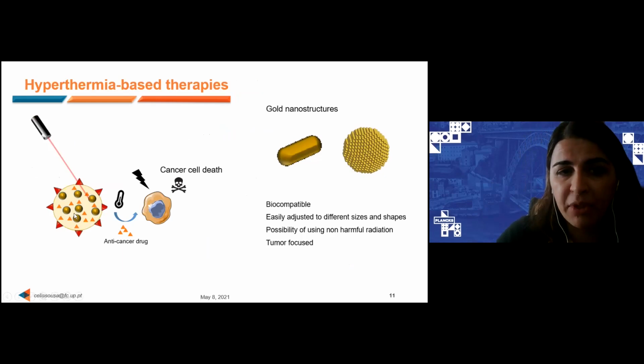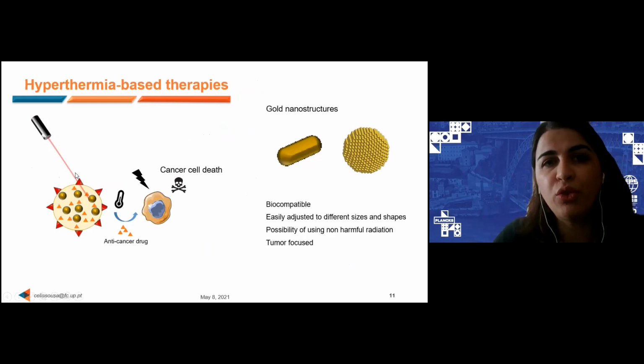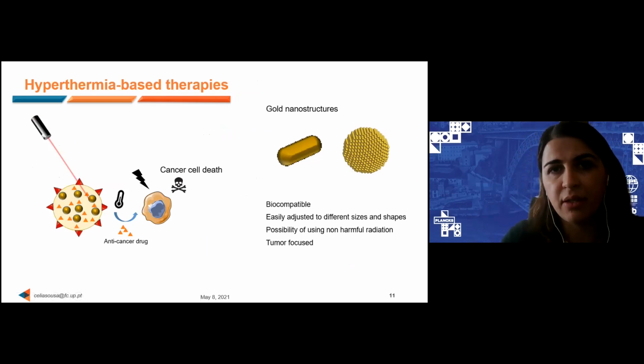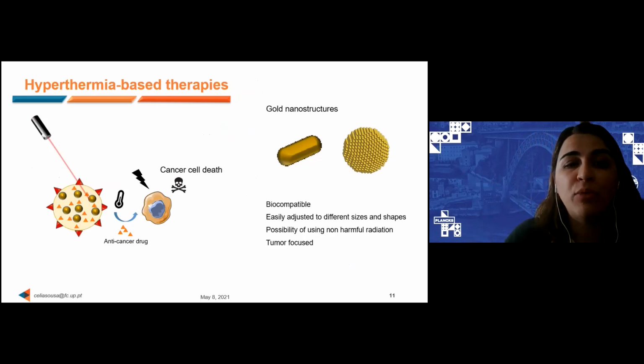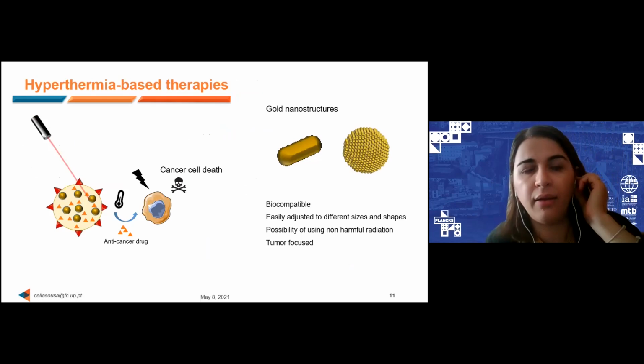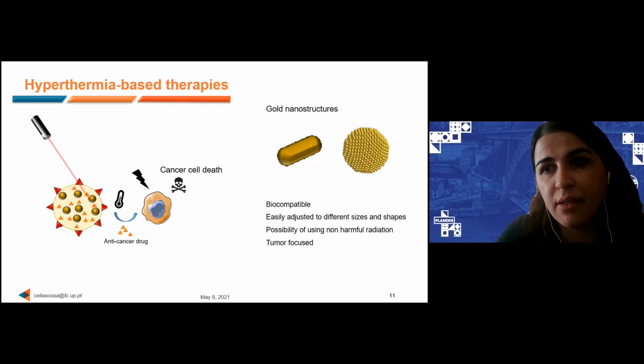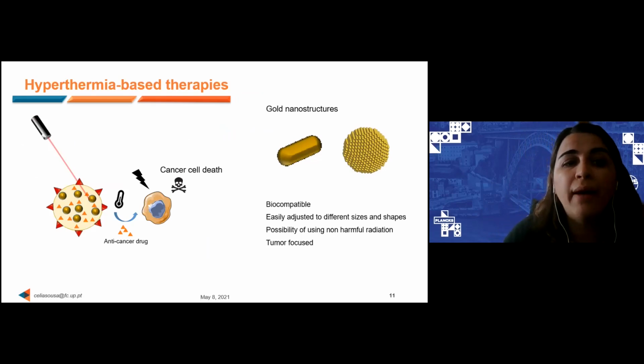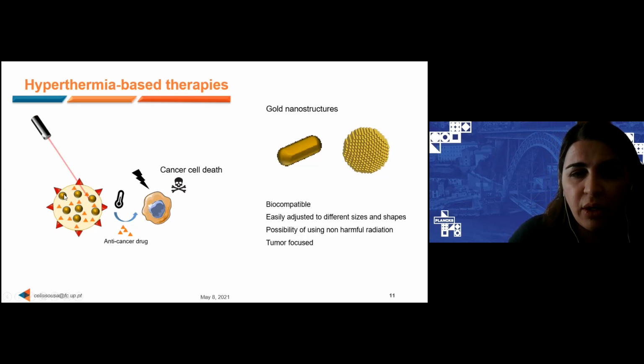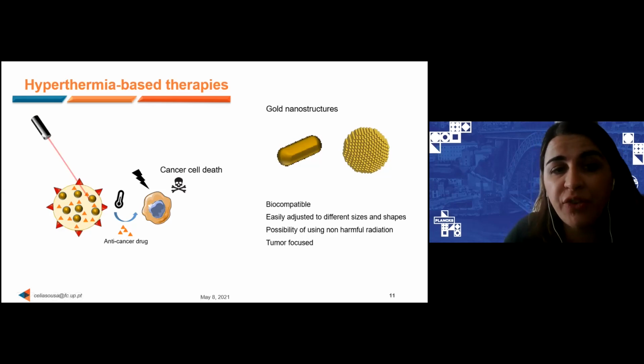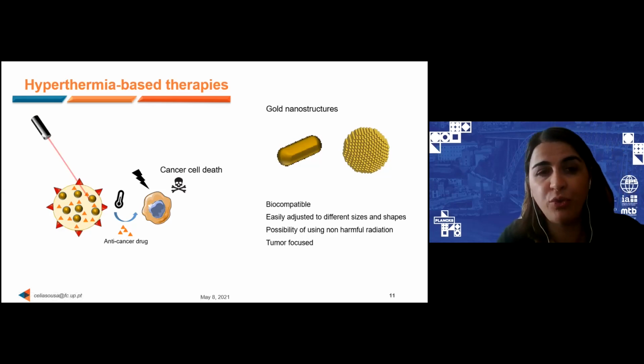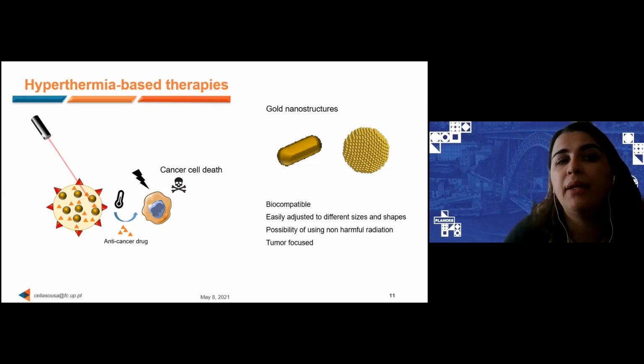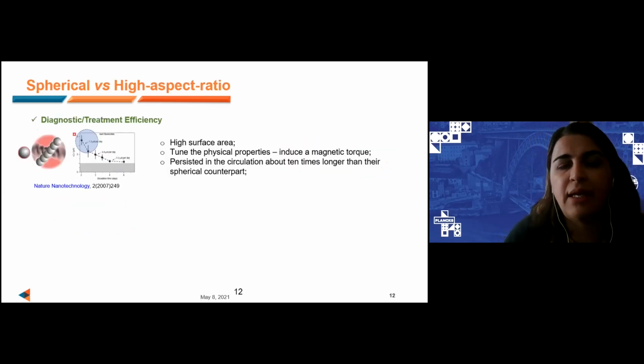We will combine our plasmonic nanoparticles with a laser. We are working with two types of lasers, continuous lasers and femtosecond lasers. And by irradiating these nanoparticles with a laser in a near infrared region where our body is transparent to the light, we are able to heat these nanoparticles and promote the drug release, the drug that is inside the lipid shell. The lipid shell will be broken and the drug will be released locally. Also, if we achieve temperatures higher than 42 degrees, we are also able to perform the phototherapy of the cells.